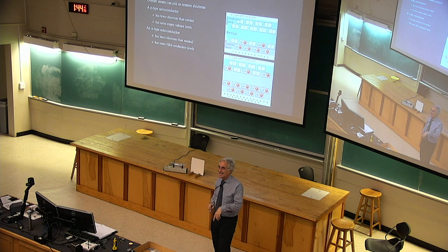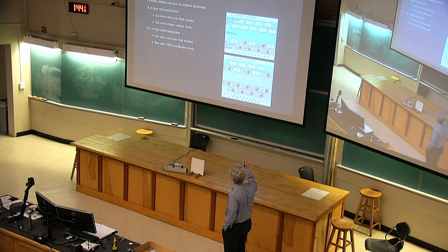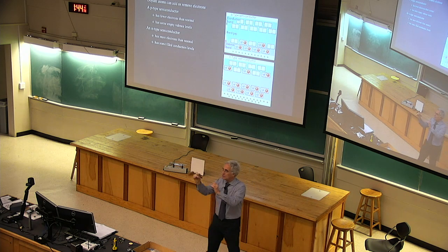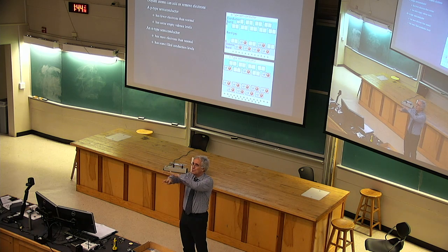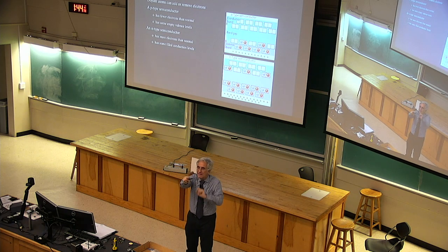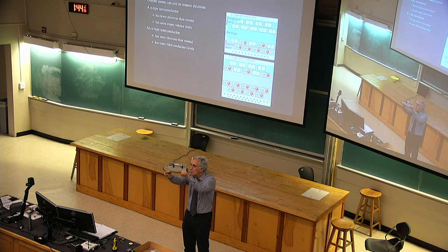Is that okay? What does that say for P-type semiconductor? Well, the weird thing about P-type semiconductor is that what facilitates the moving charge is not so much the electrons. Yeah, they do move ultimately, but it's the empty spots. Wherever you've got an empty spot, you can move an electron into it, which leaves another empty spot, which you can move another electron into. And what's kind of moving through the material is the empty spot. Like imagine this room was almost full of people, a couple of empty spots, and you can only move one seat at a time. If we watch that happen, we watch the empty spot will be there, and then a person will move. Then the empty spot will be there and move. The empty spot will be moving across the room.